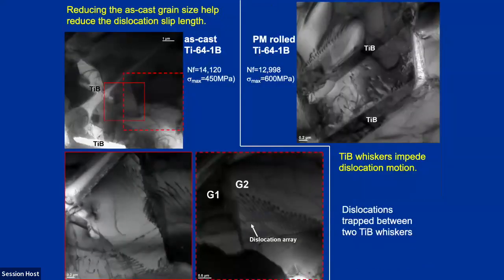And one of the things that we could look at in terms of the processing, in terms of the deformation behavior, was how the dislocations are going to build up within the microstructure. Well, we know that titanium boride whiskers impede dislocation motion. They have an orthorhombic structure. They don't have many slip systems. And we've seen buildup at titanium boride whiskers in terms of the dislocations that are trapped in them. We've also looked at dislocation structures, and they typically form and are confined within the alpha beta phase, confined between these whiskers.